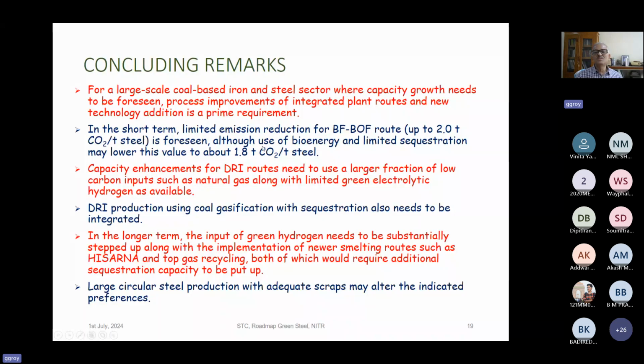Although use of bioenergy and limited sequestration can reduce this value to 1.8 ton of CO2 per ton of crude steel. By process improvement, because there is also some scope for energy optimization in the blast furnace in several places, we can reduce the CO2 emission from 2.2 to 2. And if you can use some bioenergy like biomass, you can definitely use that. And if you can do some limited sequestration, then the CO2 emission can be reduced to 1.8 ton of CO2 per ton of crude steel. That is the short-term goal.